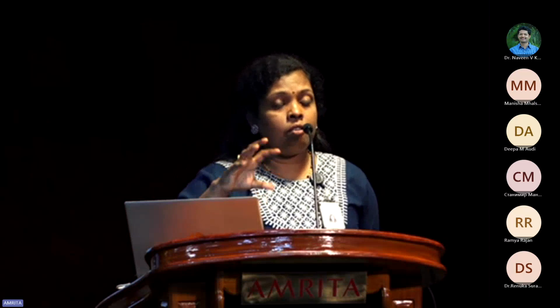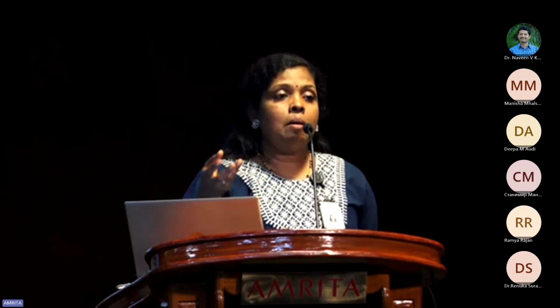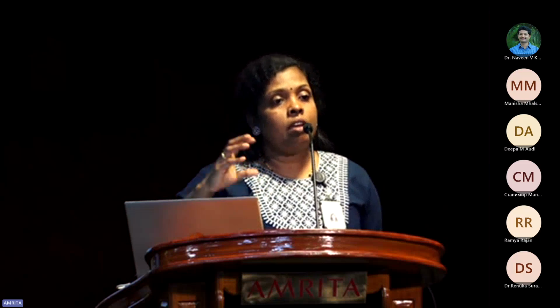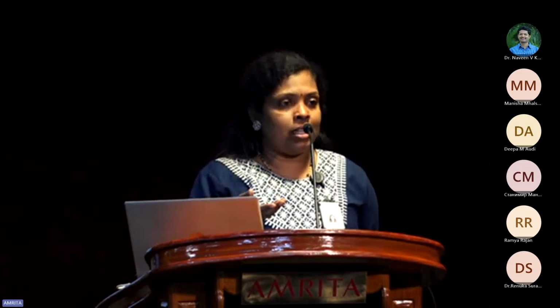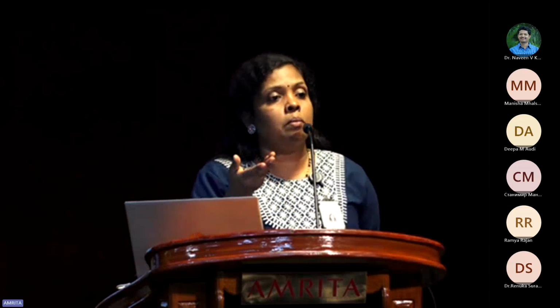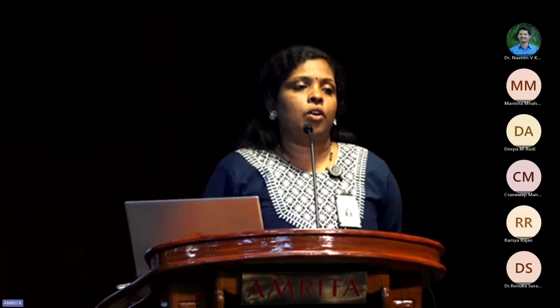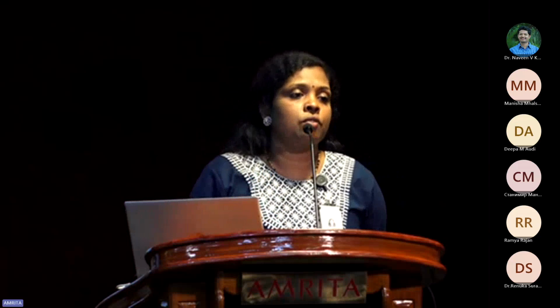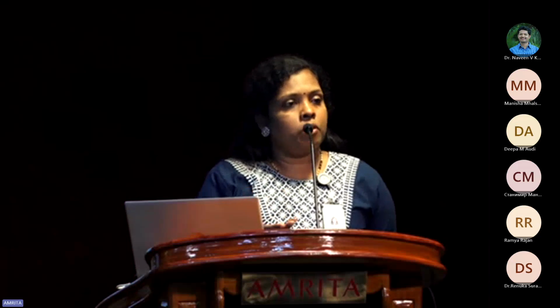Definitely the nanogel will introduce some cross-linking, but that will not be good enough; again, it is application based. What application are we looking for? If we need a high strength material, then definitely. When we choose any chemistry or composition, we have to choose based on the application. For example, in the case of dental or bone cement, the cross-linking agent or curing agent is also needed, along with the fillers.